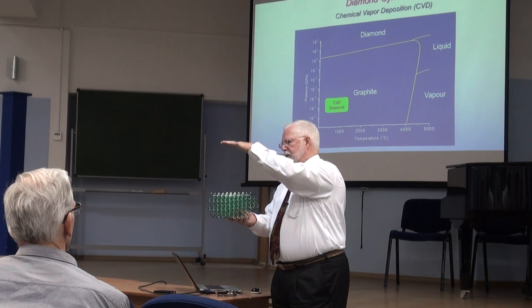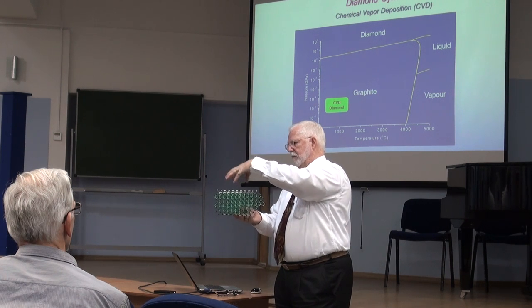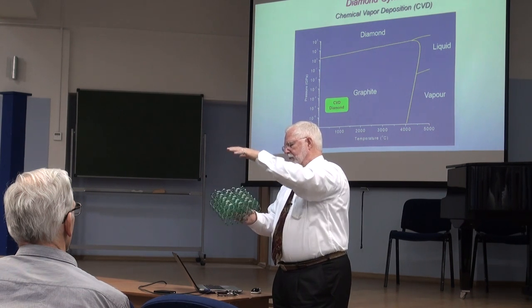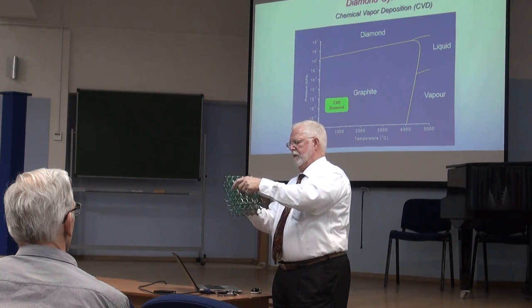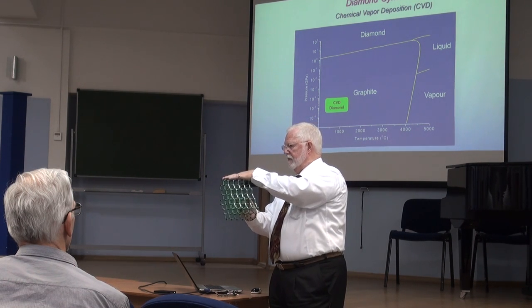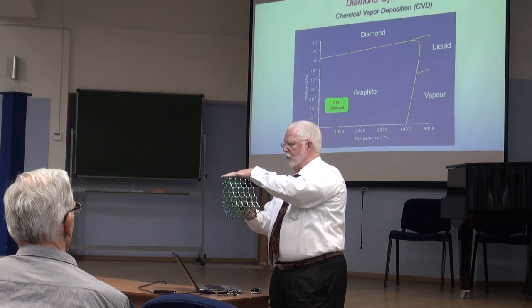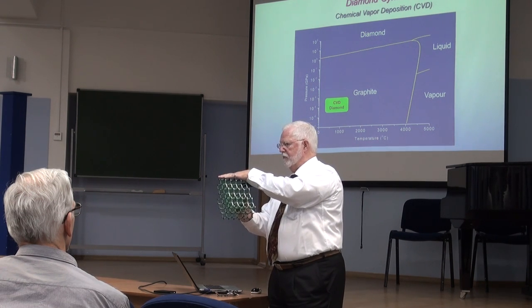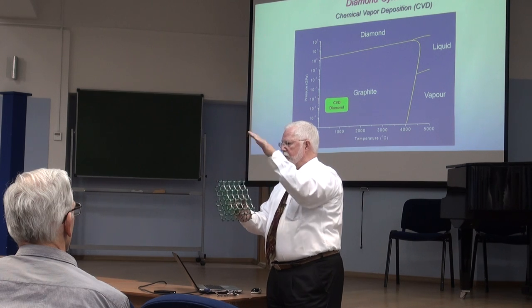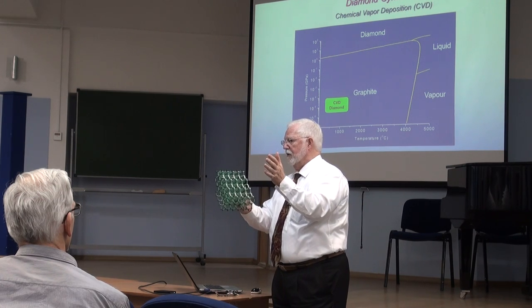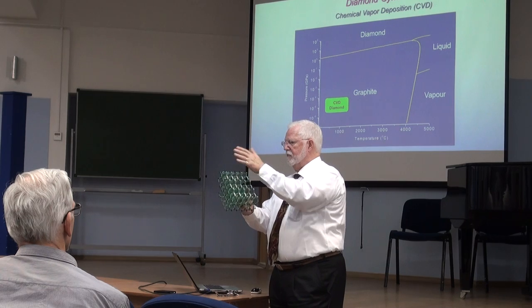The defects in that growth sector depend on the chemistry on this face. But if I grow on a 111 face like this, it has a different chemistry, defects incorporate differently, so that growth sector will have a different concentration of defects. And so you'll see slight changes in the properties between these different growth sectors.